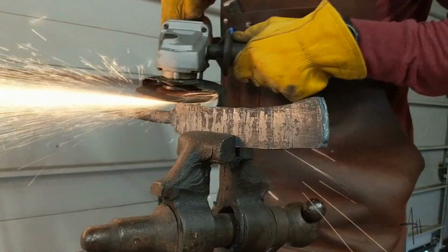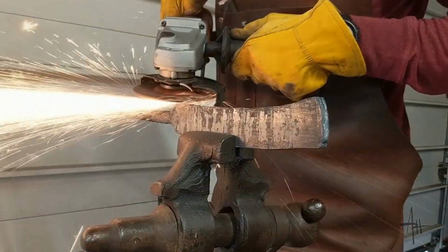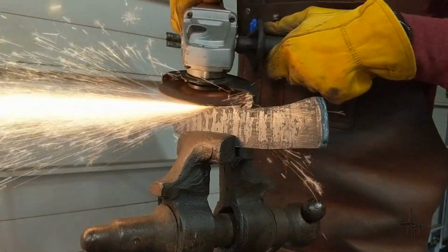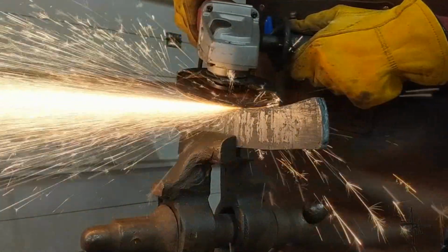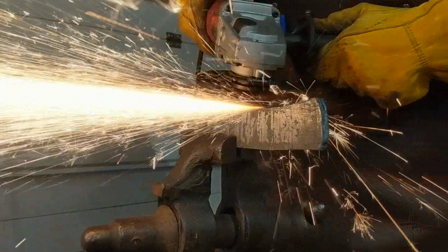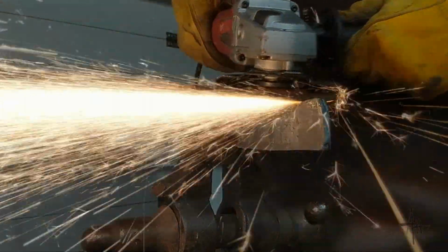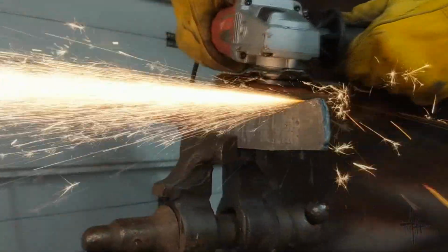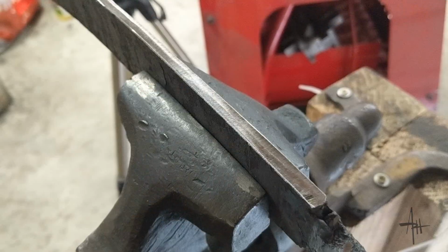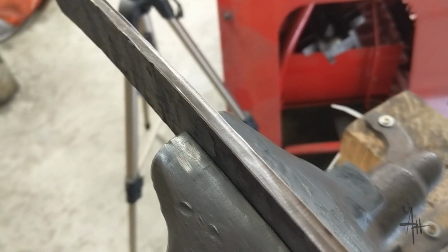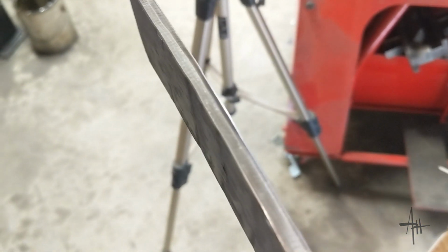Now it's time to take it over to the angle grinder and make sure that all that weld bead is ground off of there, and this is the first time you really get to check to make sure that your welds are set all the way through. It's actually pretty cool to watch because as you grind it and heat up the billet, you can see the difference in color between the stainless jacket and the high carbon core.